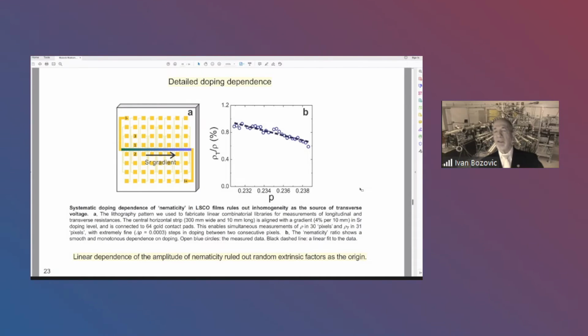And you can see that there is a systematic and linear dependence on doping. And that, of course, rules out contact misalignment and pretty much any other scenario that is based on some random extrinsic effect. Rather, I think this points to some subtle changes in the band structure and Fermi level with doping.